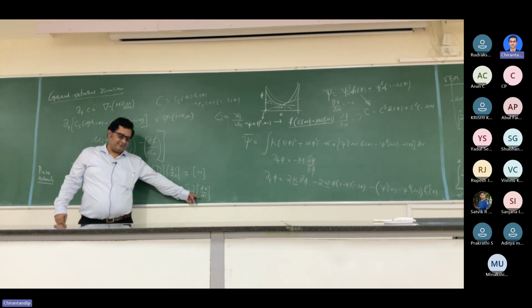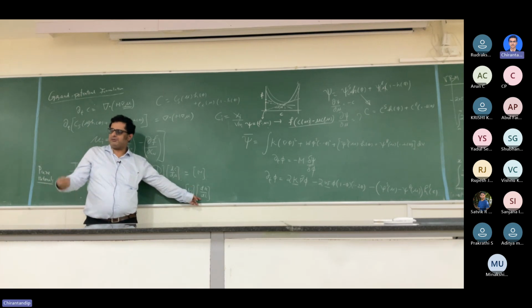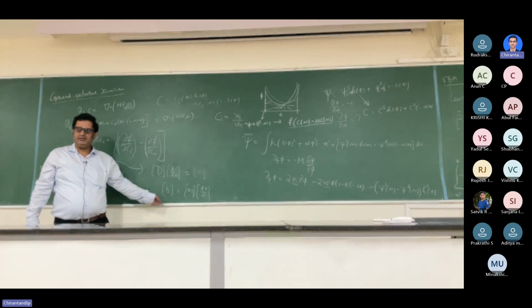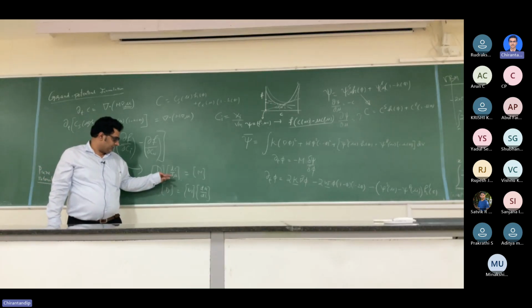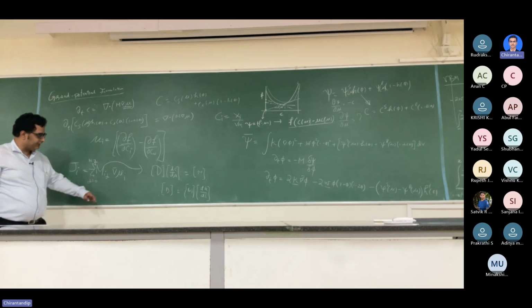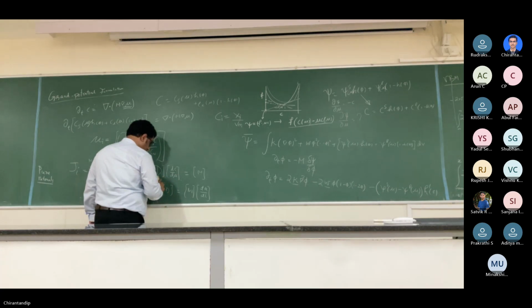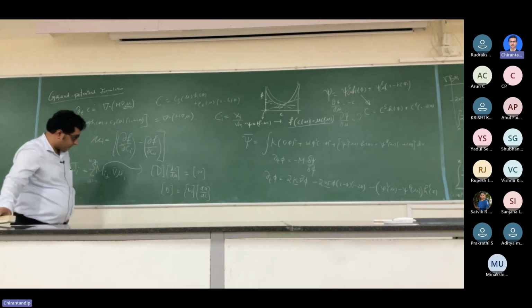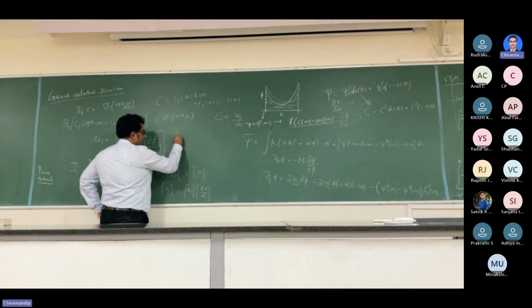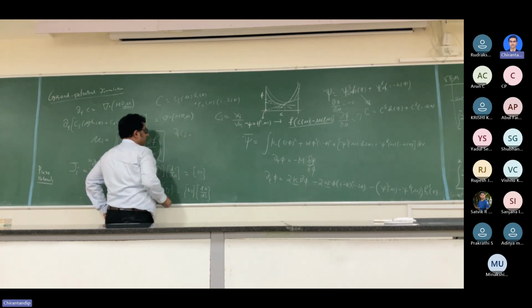This is the Hessian matrix, and this is the reason in the MicroSim software you actually need the Hessian. This is the thing that controls the mobility, as well as one more interesting property that you will see. So this diffusivity is written in matrix notation. Yes, it is correct. And once you have fixed the mobility, you essentially can just write something else.